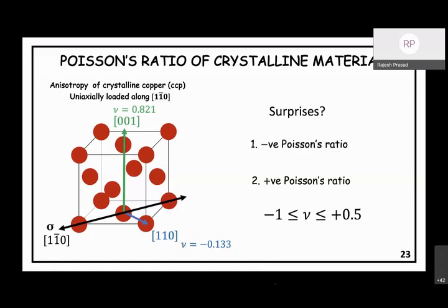You are hearing our discussion on the bounds? Yes. Do you have any comments to add to it? Yeah. So it definitely comes from the positive definiteness, and since Poisson's ratio is a ratio of two components, like S13 divided by S11 or S33. So if the denominator quantity is going close to 0, and the numerator can also be a high value, then you will see a very high value of the ratio.